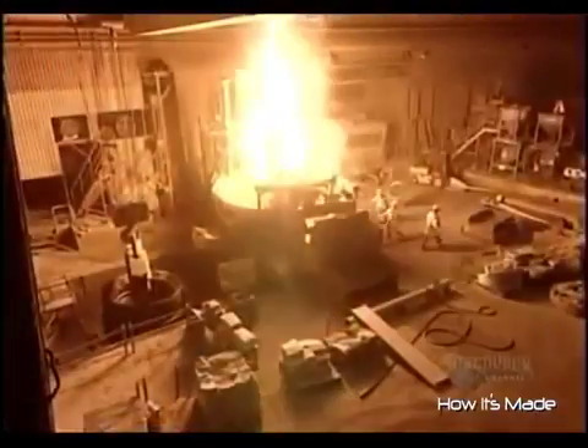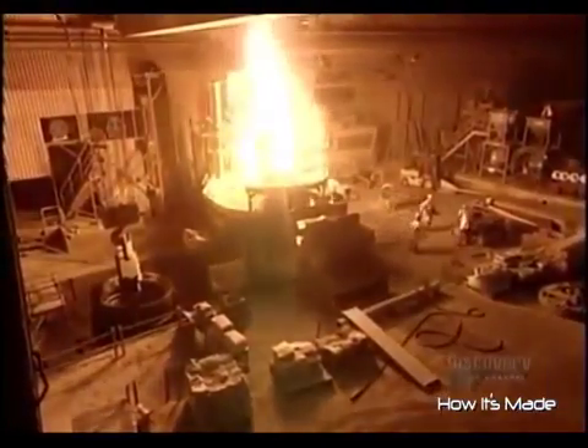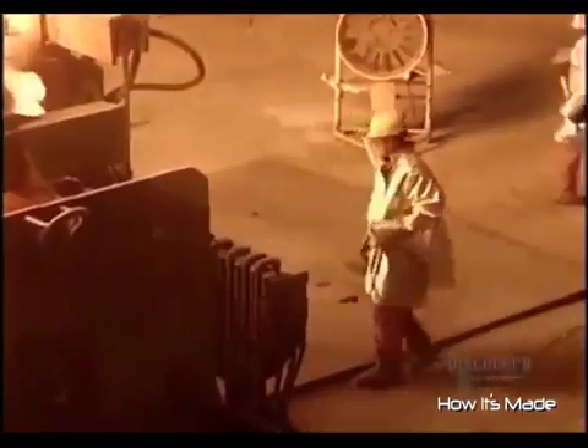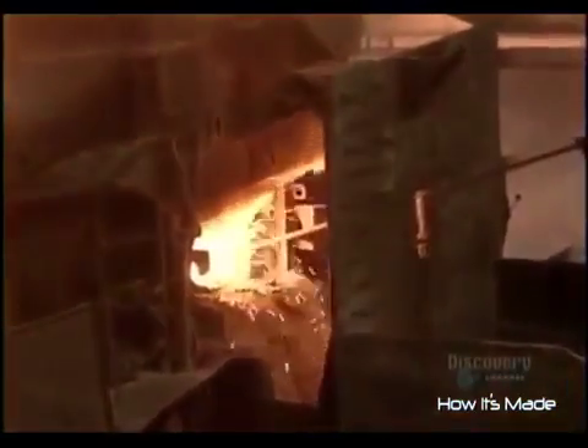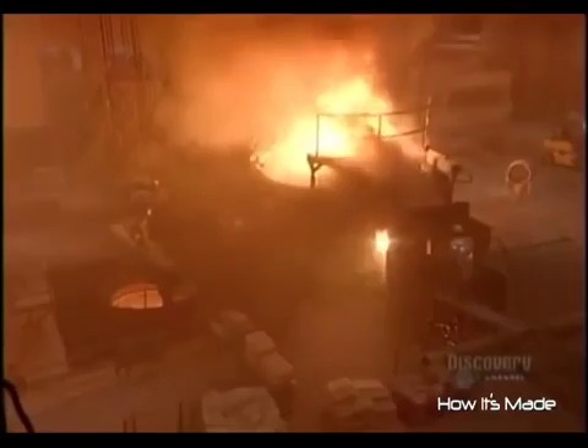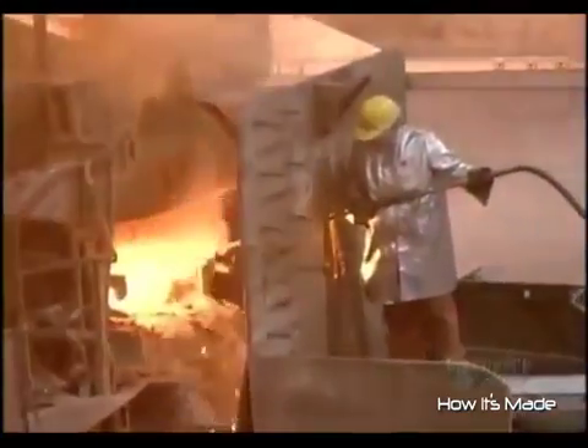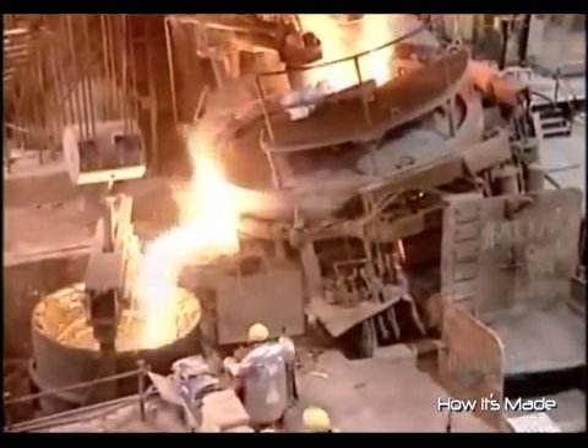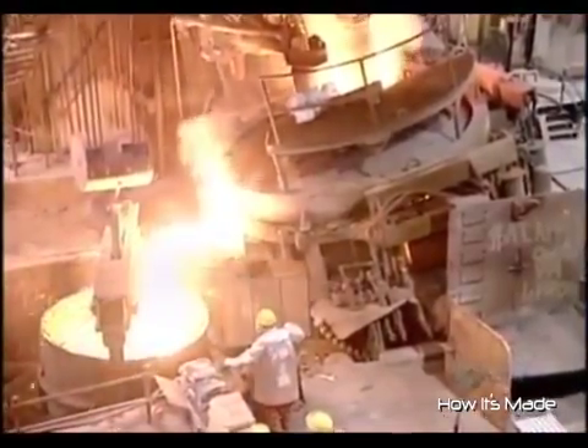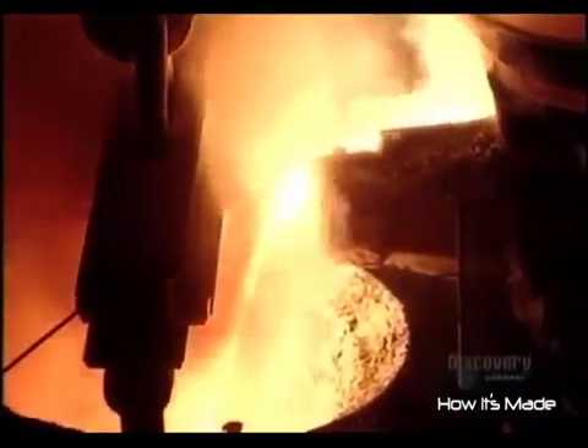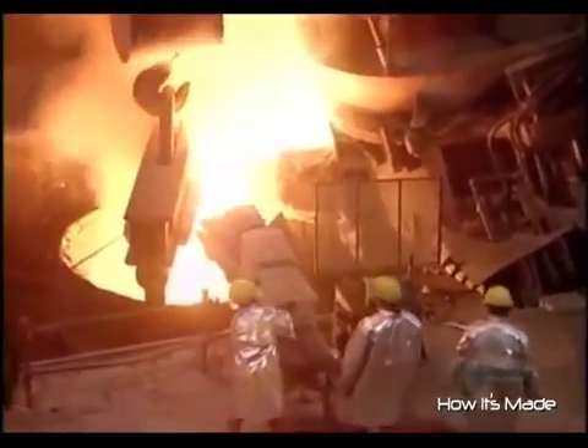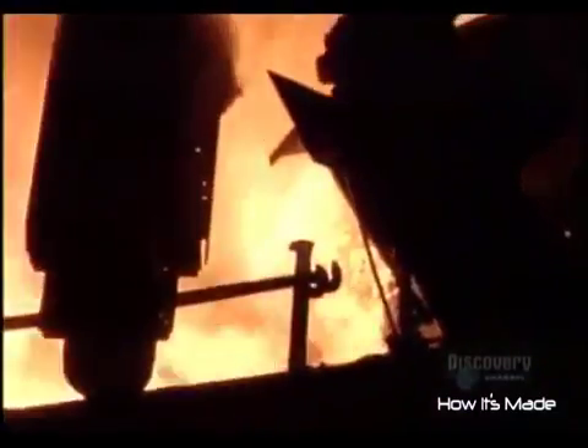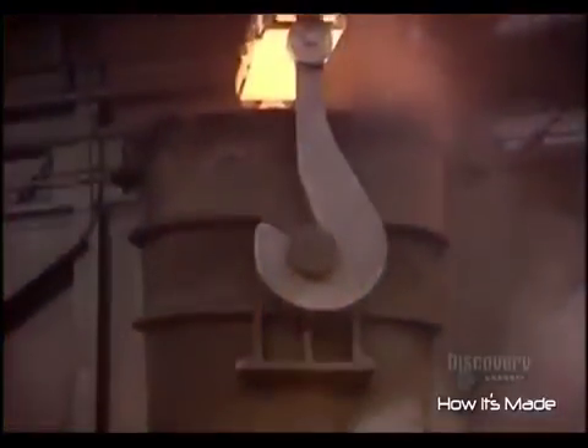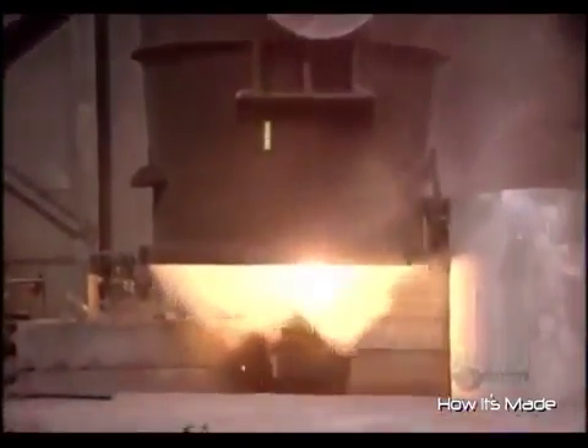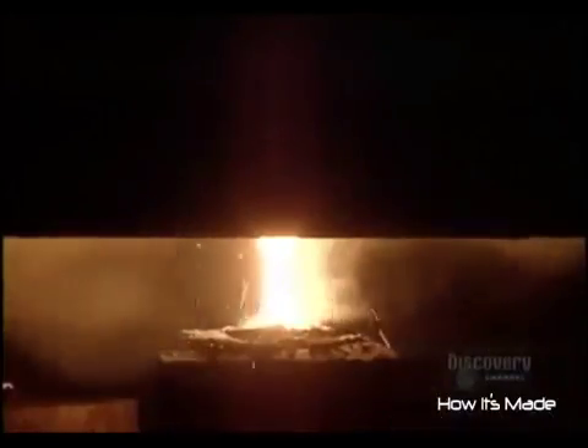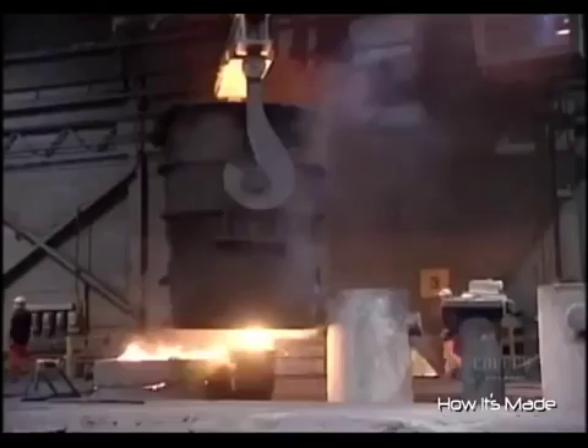Throughout the 3.5-hour meltdown, they test and adjust the chemical composition. They try to attain the lowest hydrogen, oxygen, nitrogen, and sulfur levels, the key to producing strong, high-quality steel. Then they pour the sizzling molten metal into a 45-ton ladle that's lined with heat-resistant brick. They add aluminum and lime to chemically counteract oxidization, rusting caused by air exposure. Now they cast an ingot, a block of steel that they'll shape into a forging.